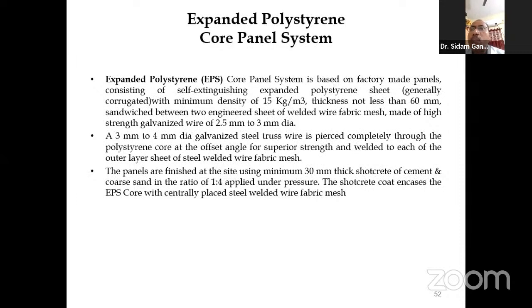Consisting of self-extinguishing expanded polystyrene sheet, corrugated, with minimum density of 15 kg per cubic meter, thickness not less than 60 mm, sandwiched between two engineered sheets of welded wire fabric mesh made up of high strength galvanized wire of 2.5 mm to 3 mm dia. A 3 mm to 4 mm dia galvanized steel truss wire is pierced completely through the polystyrene core at an offset angle for superior strength and welded to each of the outer layer sheets of the steel welded wire fabric mesh. The panels are finished at the site using minimum 30 mm thick shotcrete of cement and coarse sand in the ratio of 1:4 applied under pressure. The shotcrete coat encases the EPS core with centrally placed steel welded wire fabric mesh.